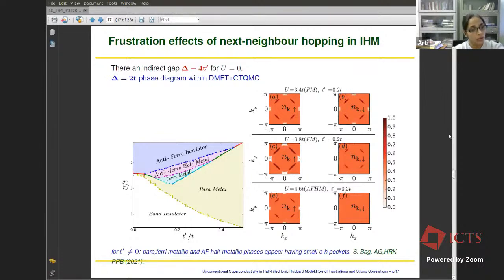Before going to the strongly correlated phase of the Ionic Hubbard model in the presence of second neighbor hopping, let's see what happens when we have interactions which are moderately strong and not really very strong. Here we show the phase diagram, again obtained within dynamical mean field theory plus CTQMC for delta equal to 2T and moderate strength of the Hubbard interaction. As you can see, for a finite value of the second neighbor hopping, the system shows several transitions from charge density wave insulator to antiferromagnetic Mott insulator via the intervening paramagnetic metal phase, then a correlated ferrimetal phase, and then an antiferromagnetically ordered half metal phase.